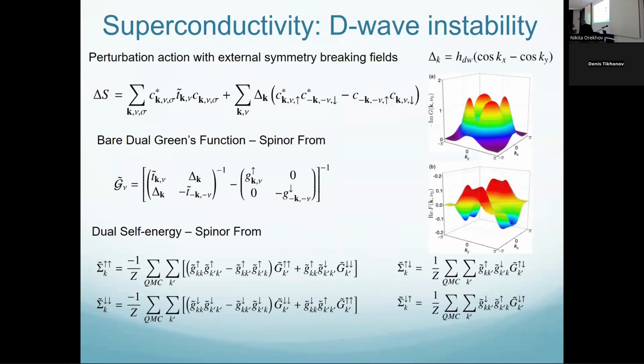In parallel to this perturbation, we can also introduce a superconducting field, D wave, and try to understand the response of our system to it. This is our first-order perturbation in Monte Carlo. And then we can calculate the normal Green function as a function of K in this Brillouin zone, and the anomalous, this Gorkov Green function, which is related to the delta. And then you see it has very nontrivial properties. First of all, it's almost like D wave. So the order parameter is positive, negative, positive. It's a D wave, no question.